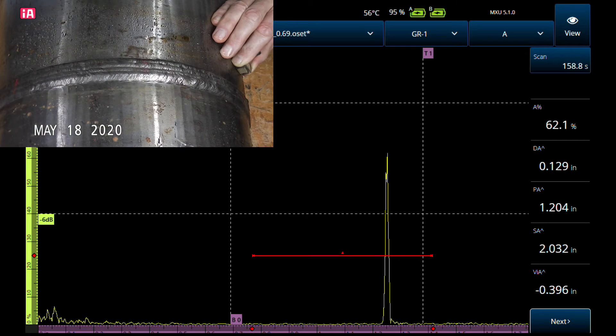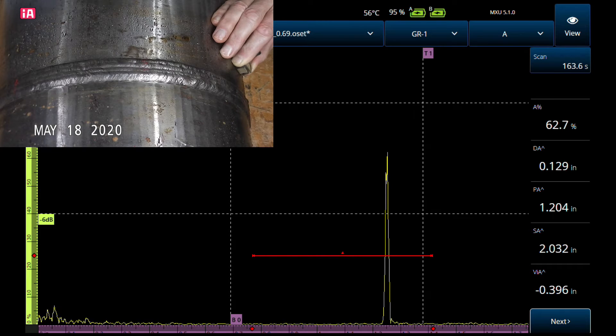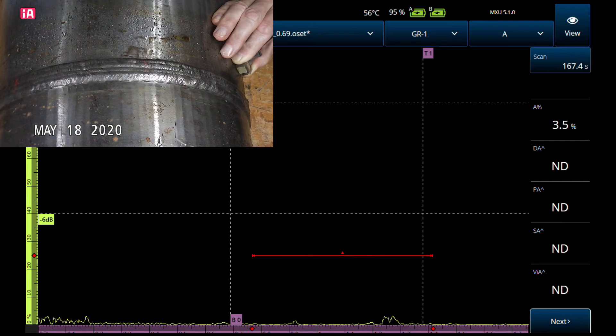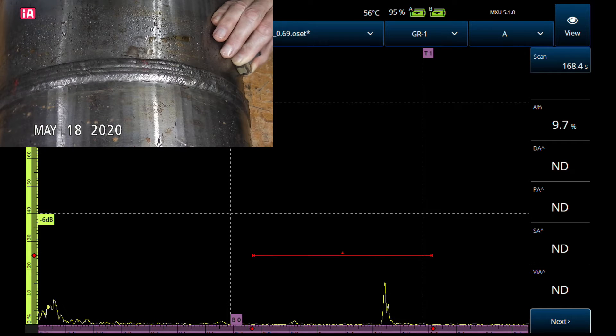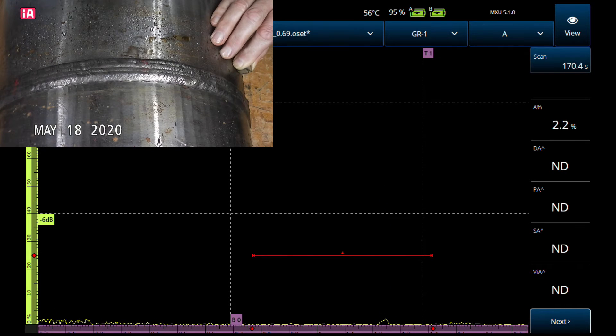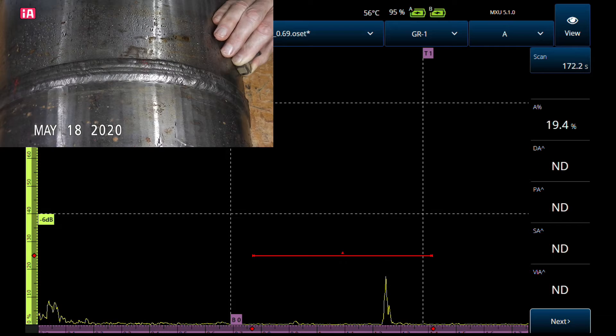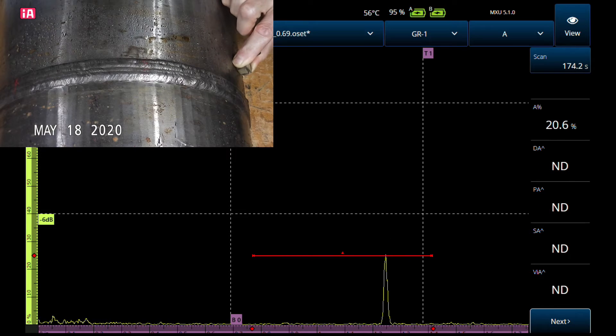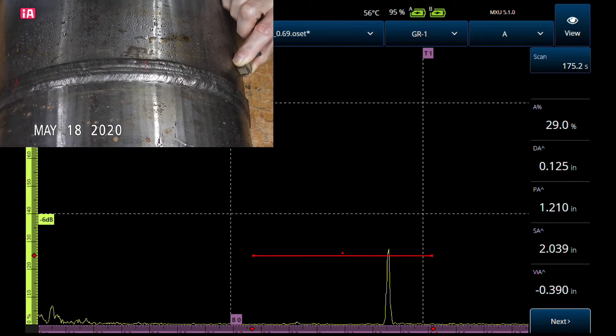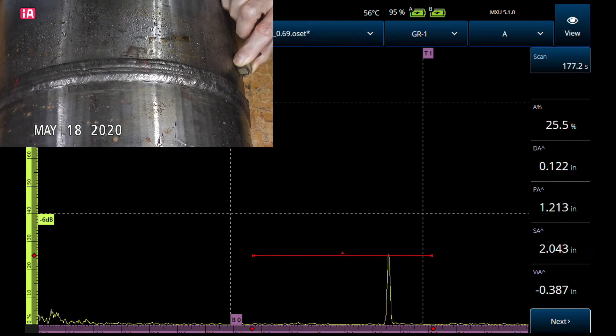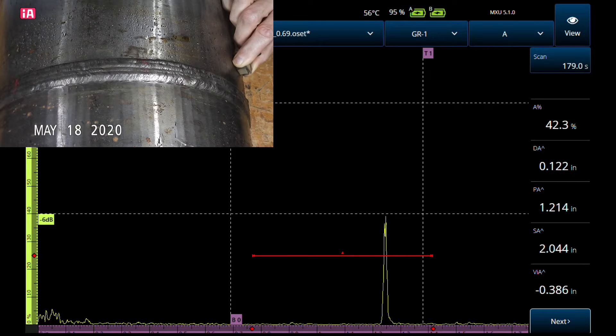Let's see what happens when we skew the probe and look at the signal. Since this is like a mirror and it's smooth, as soon as I start to skew the probe that signal should just drop straight down. There's nothing else on that flaw to keep the signal to reflect. Look how little I'm skewing that probe and it just drops right off.